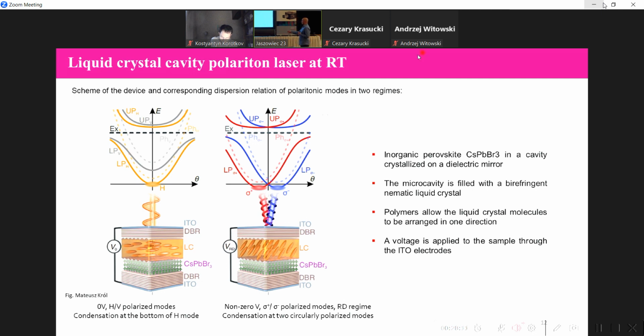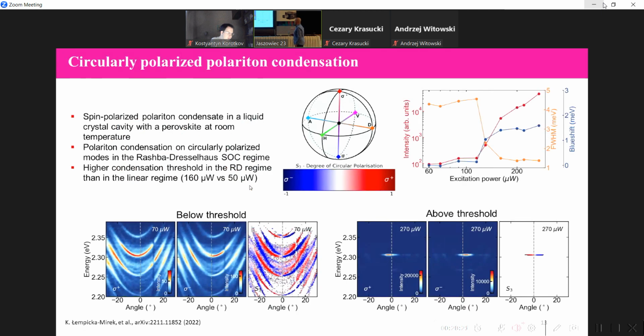These are the visualizations in the linear regime - linear meaning linear polarization, not linear in power - and the circular regime. In case of the results, there is a possibility to polarize polariton condensate in the liquid crystal cavity with a perovskite at room temperature.